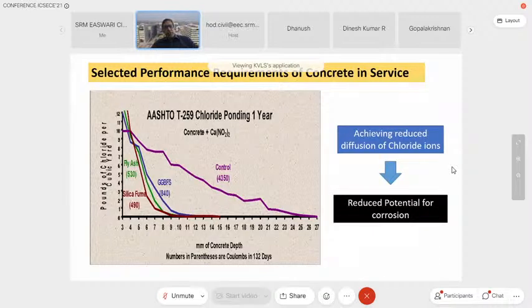So just to show you how this could be achieved, I'm showing you the performance of concrete against chloride penetration. This becomes very, very important when we are dealing with concrete in a marine environment. The test is done by the ponding test, the AASHTO test, where you pond concrete with salt water and you see how much chloride penetrates into concrete. Now, this is a control concrete, which was basically designed using OPC.